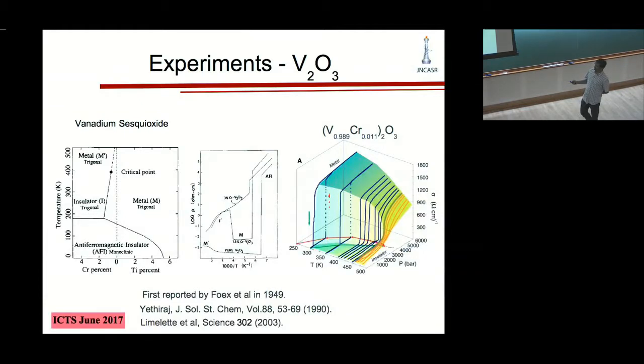In fact, the experimentalists report that at these points where this transition happens, the crystal actually cracks and there's a big sound. And these are old experiments, but the same experiments were repeated in 2003 by the same group. George Honig was the sample, in his lab the sample was prepared. And what you see here is again pressure, temperature and resistivity, conductivity in fact. And if you sweep through the pressures, then you see hysteresis. And what they report is that they can go as slow as they can, but still the hysteresis remains.